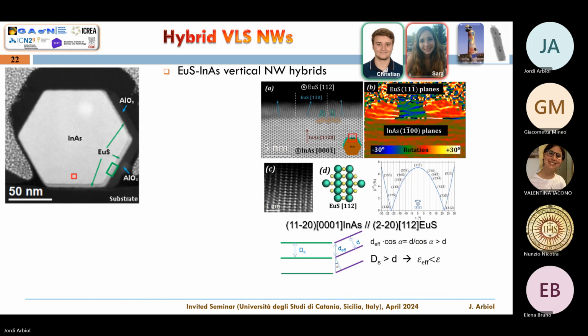And then let me see if I can show you. Okay, can you see this is the beautiful structure of the indium arsenide? It's a hexagonal structure, super beautiful. But then on top, you see that there are a kind of grain boundaries, and they are flexing or rotating slightly, so they are not perfectly adapted. So the point is that the answer is here. If you want to adapt these two materials, what you need to do is get exactly the same lattice parameter.